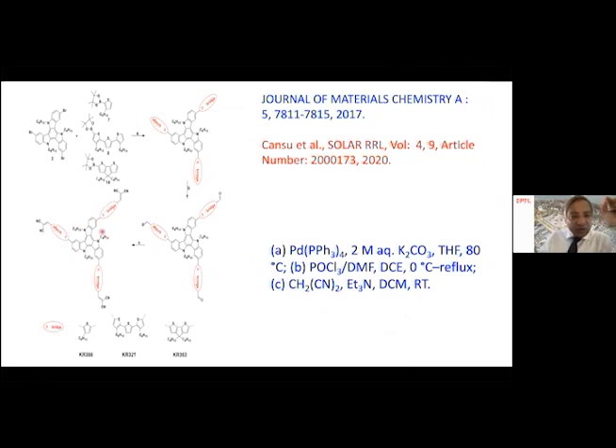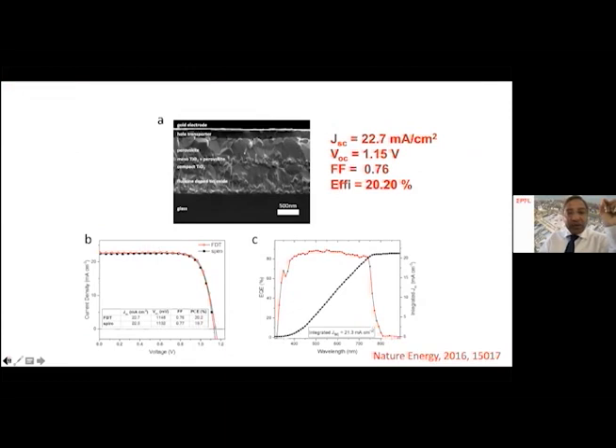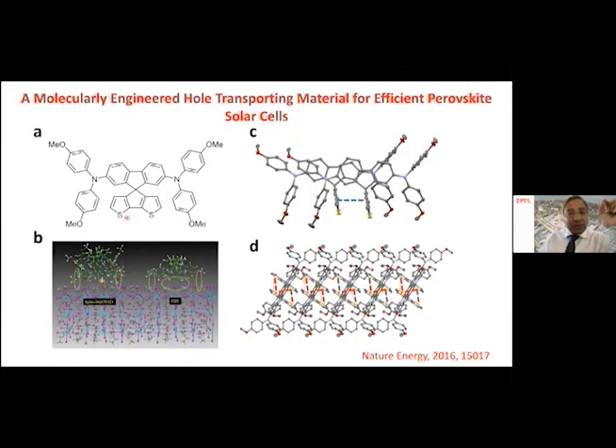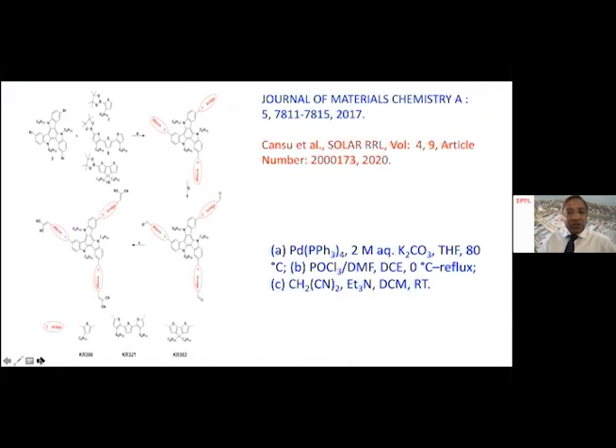That's a flat molecule with a core. Let me just go back one slide. So here, if you look at the groups, it's a bithiophene. The purpose of keeping this bithiophene is to enhance the interaction between the perovskite and the sulfur groups. And they interact significantly and give you better interfacial interaction. Similarly, here we have created the same thiophene groups.